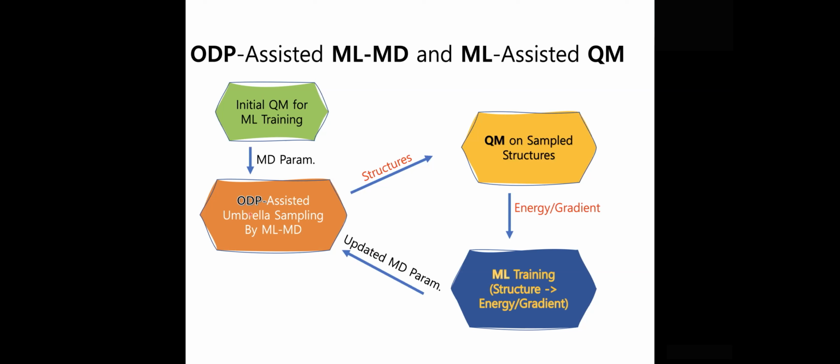Using these, we can map out any kind of structures you can obtain. This is in fact the free energy surface, which is not the potential energy surface you get from quantum calculation. This free energy surface includes entropy effects too, so this is really the complete information. Here you can see the interesting points. By the way, this kind of free energy surface cannot be generated by quantum calculation because it requires so much data. But with these machine learning fitted parameters, there's no problem, right? So maybe I should first point out that this might be the first free energy surface calculation without using quantum calculation.